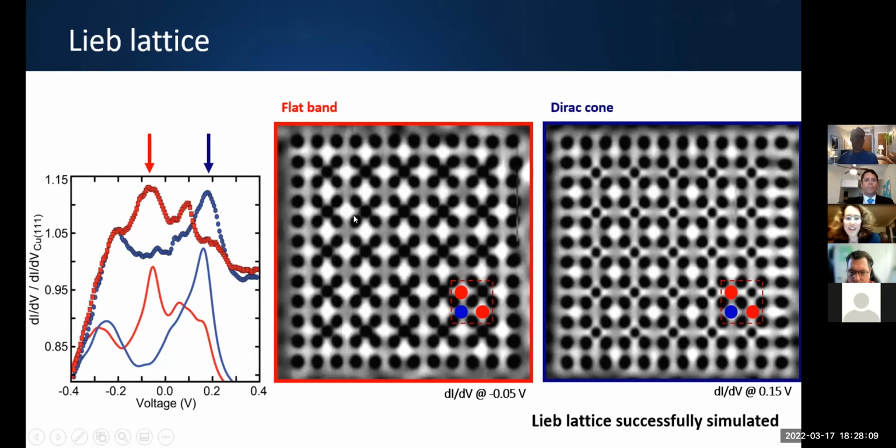They are not moving around, but indeed we could use two types of techniques to measure this. In this case, the electrons are basically stationary. They're trapped. Yes, they are trapped, and in this case, they are even strongly trapped because this flat band has a high, what we call density of states. And it's quite narrow. It means that they are very localized here.